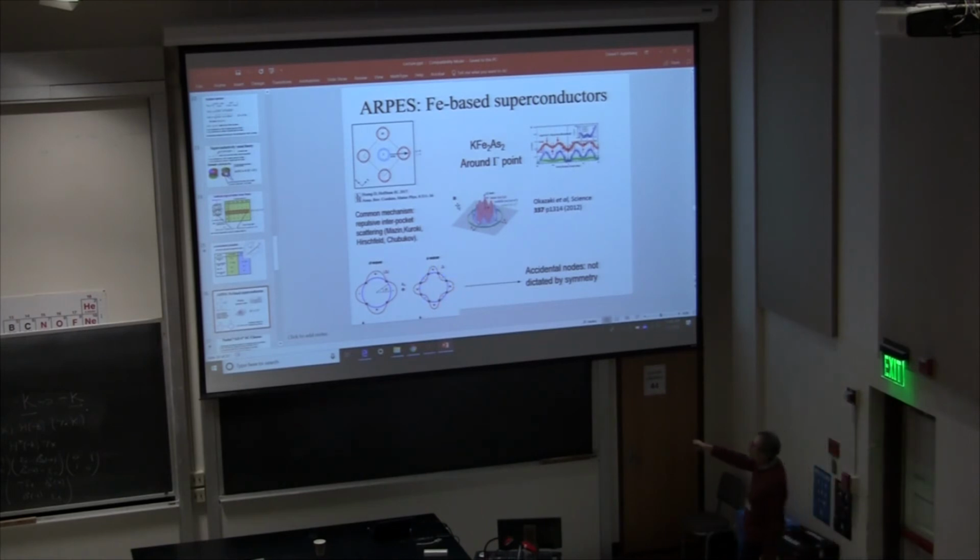But if you look at these two pictures, remember in the D-wave state, if I did a 4-fold rotation around here, the minus goes to plus, I pick up an overall minus sign in my wave function. But here if I do a 4-fold rotation about this point, my plus goes to plus. And so formally this has the same symmetry as S-wave.